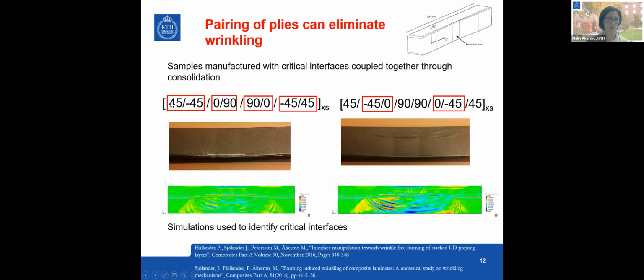So based on that, we can actually understand and predict why this behavior happens. We saw that if we have a 45 minus 45 and a 0-90, and you form the pairs separately, you have no wrinkles. But if you start putting them together, you will have that. So we could also simulate and show that if, instead of forming 2 layers at a time, we put everything together, but we forced the layers that we knew gave us a good result to work hard together, trying to make the interface between the different stackings here weaker, we could get the same good geometry as when we did them 2 by 2. So the simulation could help us understand what happens, and we could verify it.